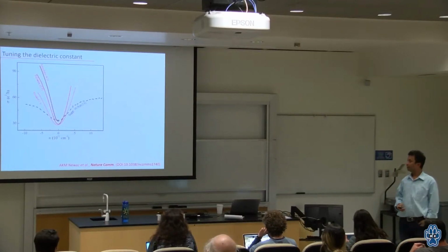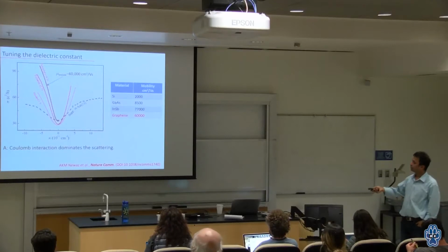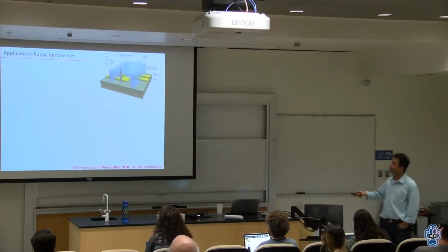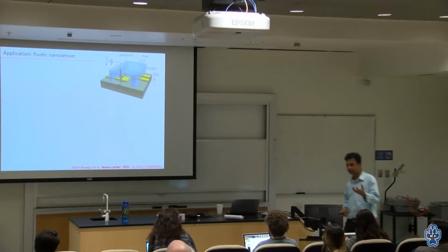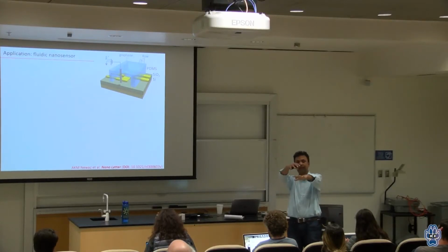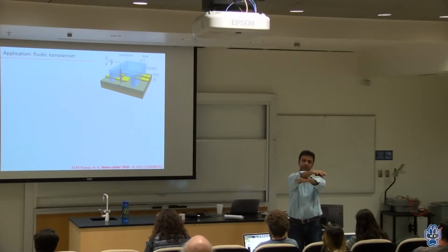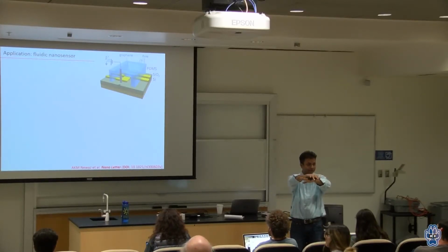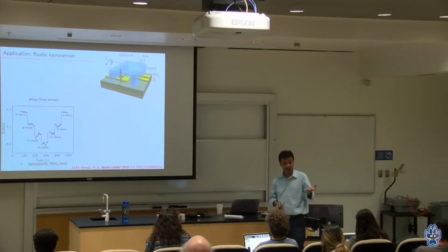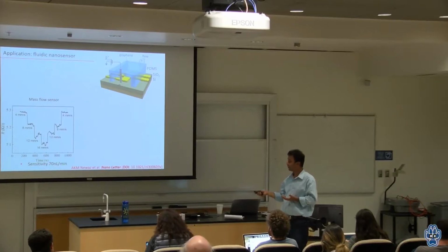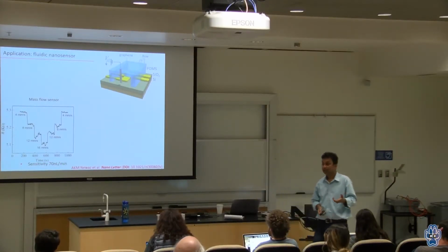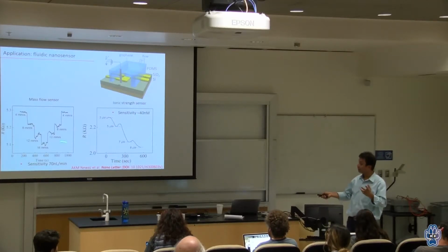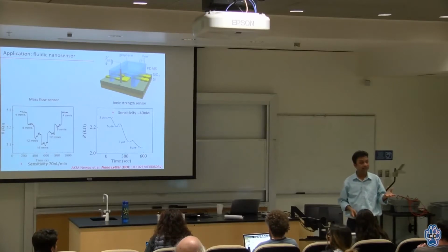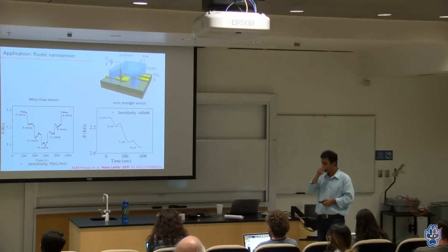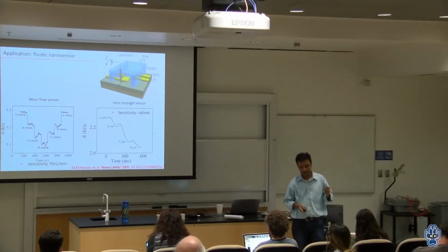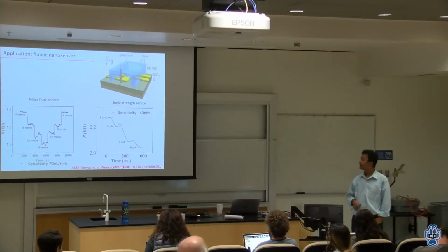So what is the application of that? One of the applications we did, we extended that experiment further, because graphene is the most sensitive charged material. We made a graphene transistor, put a microfluidic channel on top, and flowed liquid on top of it, to study whether you can measure the flow velocity. Indeed you can. The sensitivity of our devices was 70 nanoliters per minute. And not only the flow velocity, you can also measure the ionic strength in the material. So it has dual sensing properties.